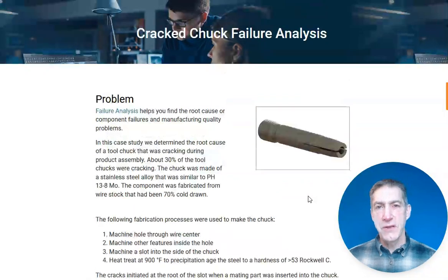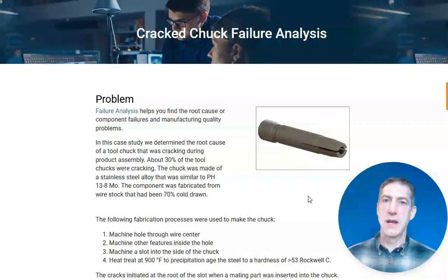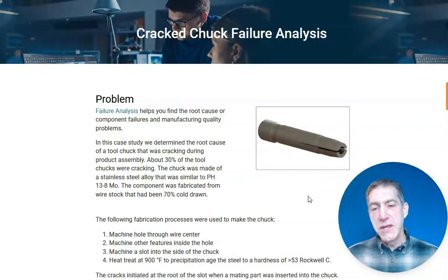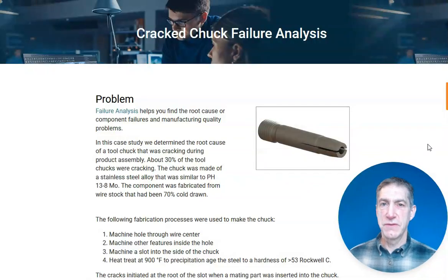So for the failure analysis, we did scanning electron microscopy of the crack surface, also looked at the microstructure, and measured the hardness of the material. Looking at the fracture surface and at the microstructure, we determined that the material was failing in a brittle manner. The heat treatment that was used, H900, results in high strength but also poor fracture toughness for the material. That means it has a high susceptibility to cracking where there is a stress concentration,